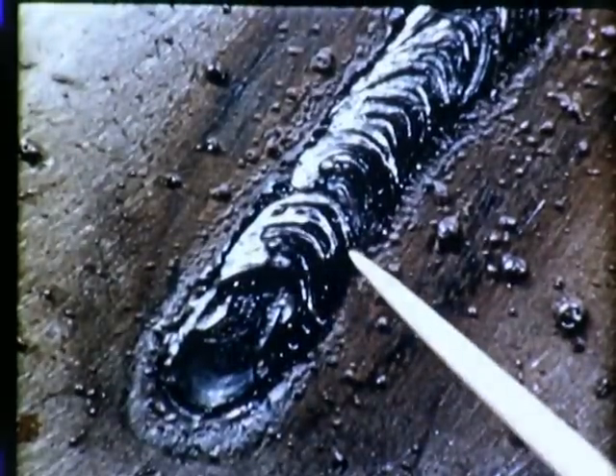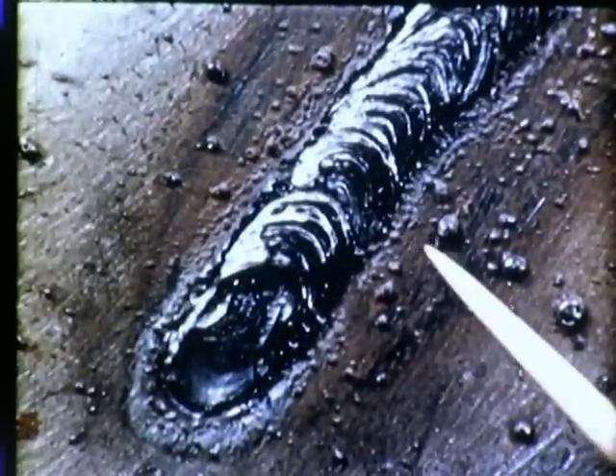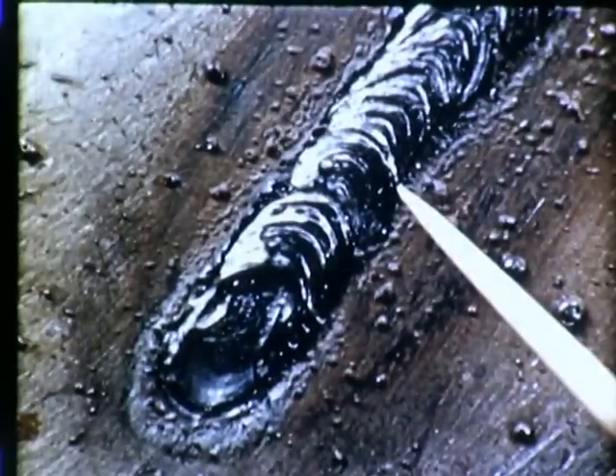If the arc is too long, the metal melts off the electrode in large globules. These globules drop on the work in a form of spatter instead of going into the molten pool as useful metal. A wide, spattered, and irregular bead is formed. The weld metal is left on top of the plate with poor fusion between base and deposited metal.